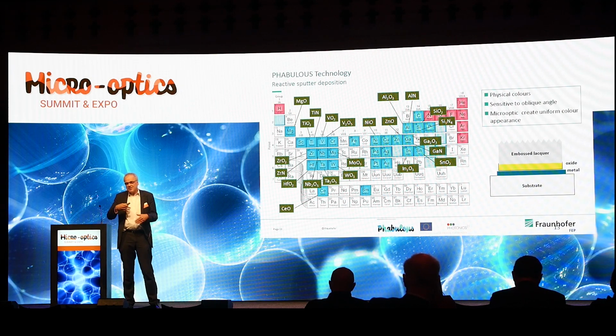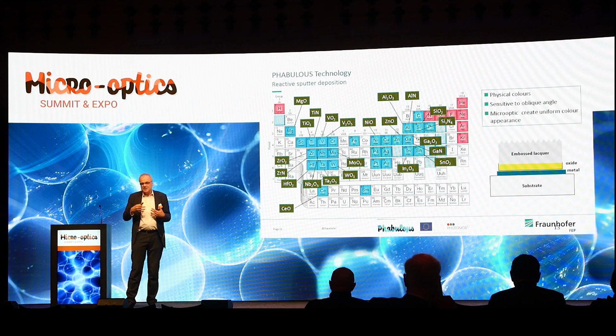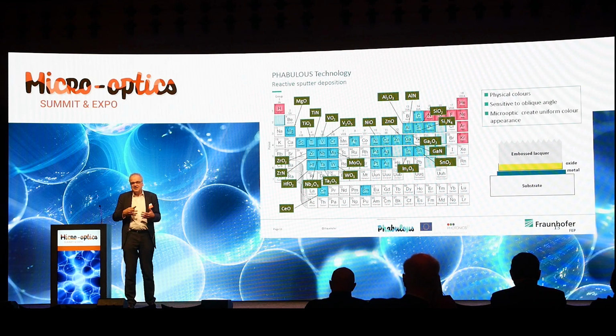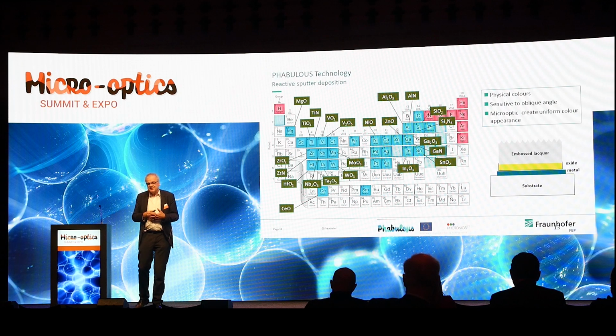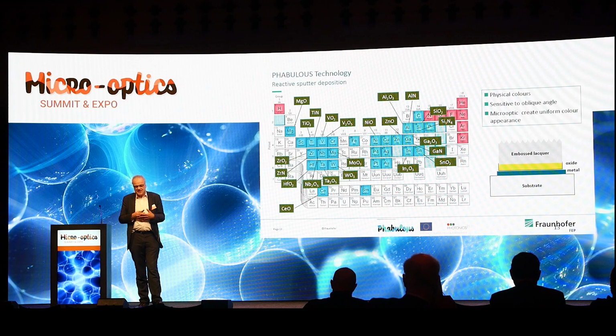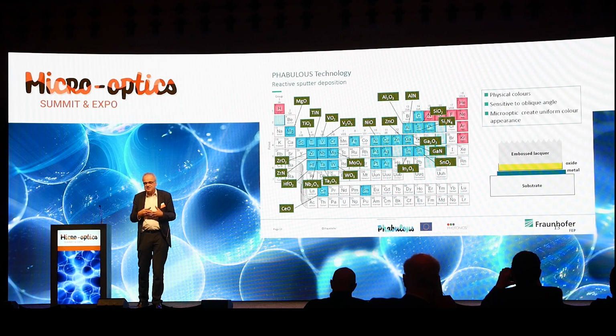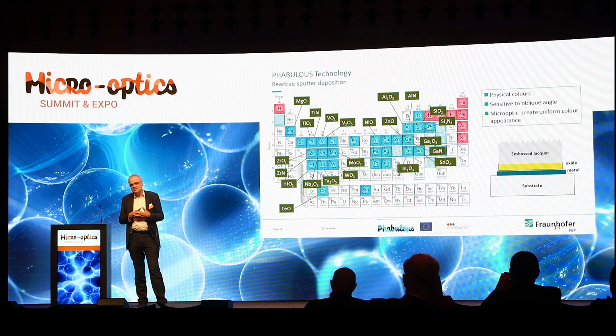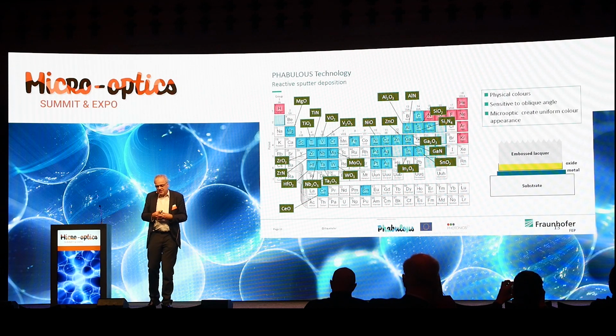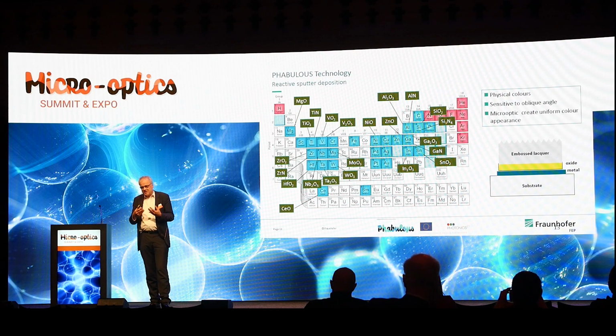Normally sputtering is something where the target is a part of the electric circuit, so you are somehow dependent on the fact that the target material is electrically conductive. But with the special technology of the reactive sputtering, you can overcome this restriction, and you can make a lot of compounds, especially oxides and nitrides. And this is something which is quite important for optical coating and for also the expertise which we brought into Fabulous, because these oxides and nitrides are quite important for achieving optical effects.